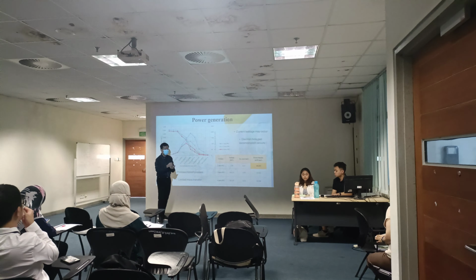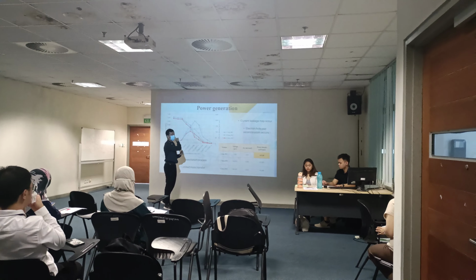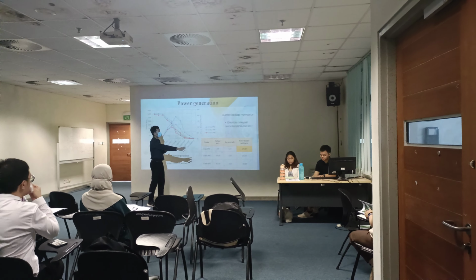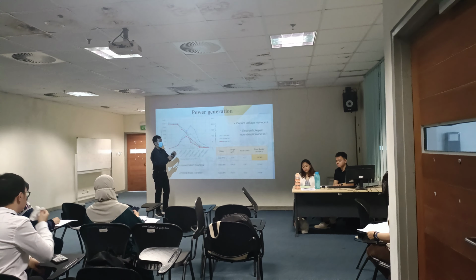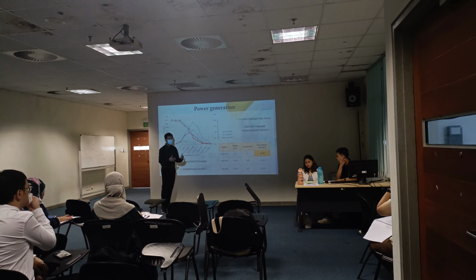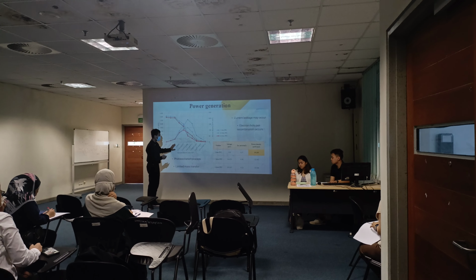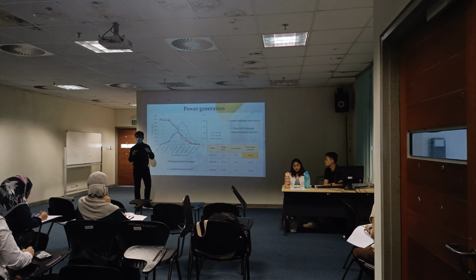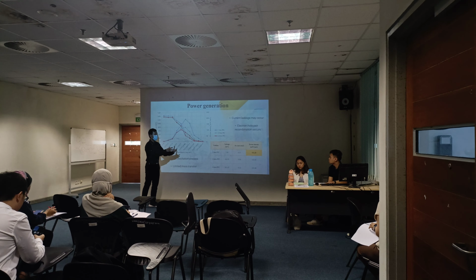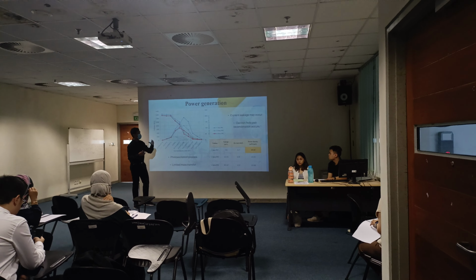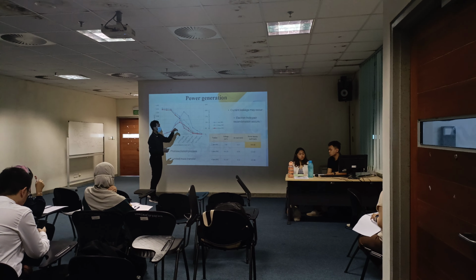This is because the photogenerated electrons produced need to travel a much longer distance to reach the cathode chamber, which means they are more susceptible to unintended reactions. For example, the photogenerated electrons will react immediately with oxygen molecules in the anode chamber instead of traveling through the external circuit to the cathode chamber. When this occurs, less electricity is produced because the electrons don't travel through the external circuit.